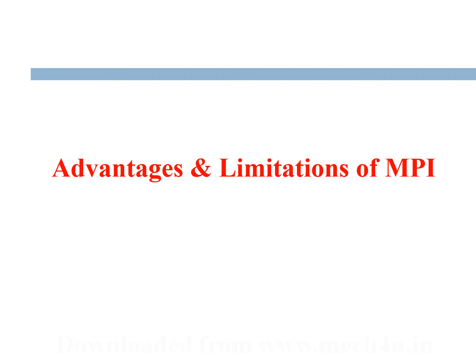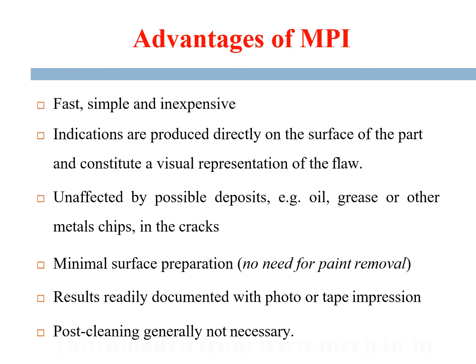Now, we'll also discuss the advantages and limitations of the magnetic particle testing methods. The advantage is that it is fast, simple, as well as inexpensive. Indications are produced directly on the surface, and a visual representation of the flaw is directly obtained. They are unaffected by possible deposits such as oil, grease, or metal chips in the cracks. Minimal surface preparation is needed, that is, no need for paint removal, and less pre-cleaning is needed.